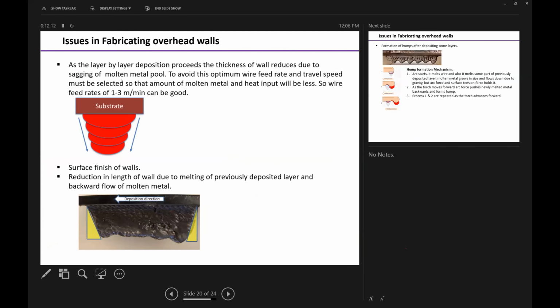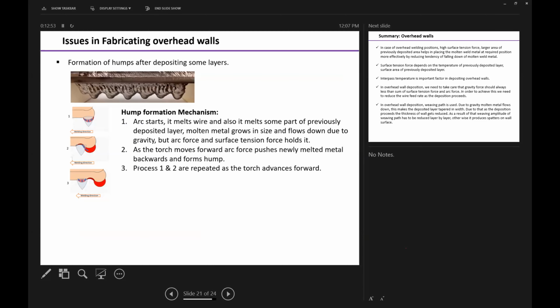So the issues we are facing in fabricating the overhead walls are, first, as the layer by layer deposition proceeds, the thickness of the wall gets reduced, because the molten metal moves downward or flows down due to gravity. The second issue is the surface finish of the wall. The third issue is the reduction in the length of the wall, due to the melting of the previously deposited layer and backward flow of the molten metal. And the fourth problem that we were facing was the formation of humps after 2 to 3 layers. So we are working on this.